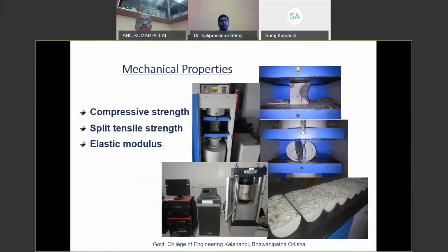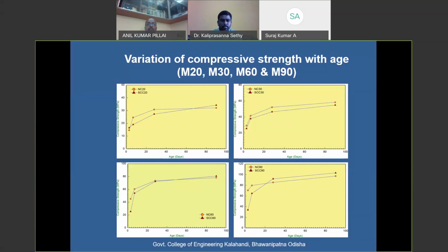So with this we'll move towards our mechanical properties like compressive strength, splitting tensile strength, and elastic modulus of the developed concrete. Here is the graphical representation of the observed results which we have obtained by using the CTM machine for the compressive test. The graph is plotted between the duration of ages in days and compressive strength. We have tested it for 3 days, 7 days, 28 days, and 90 days. There are secondary reactions which take place in the case of supplementary materials. When you use supplementary material, we have checked the 90-day strength for self-compacting concrete.